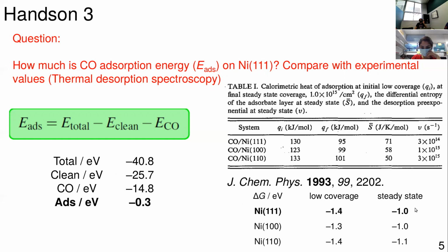Okay, that is just again to highlight what we were discussing with you last time, that surface coverage, whenever you talk about adsorption, is very fundamental. Because depending on the surface coverage, you see here the energy is changing by 0.4 electron volt, and that's a lot. So just remember, whenever you need to calculate something, try to understand what the coverage is, or calculate different coverages theoretically, and say, look, at this low coverage I have this value, medium coverage this value, high coverage this value. So at least you have an idea of how much is the mistake or the uncertainty.